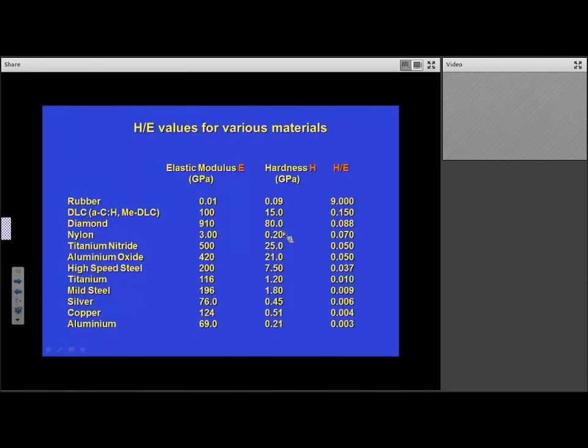And of course we can put that onto more consistent units now. We can define elastic modulus in gigapascals, and we can define hardness in gigapascals as well. And what we find is that materials with a good wear resistance tend to have a H/E ratio of about 0.1 or higher. As you can see here, rubber is very high, but that's a special material, and obviously we can't make engine components out of rubber, but we can use rubber for other things like tyres. But our aim in coatings development is to try to develop coatings with a H/E greater than 0.1. It's a good objective to have.